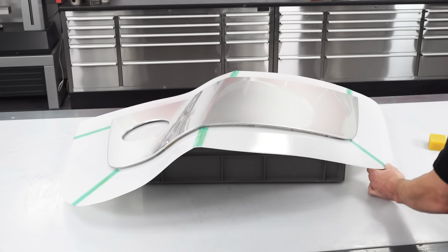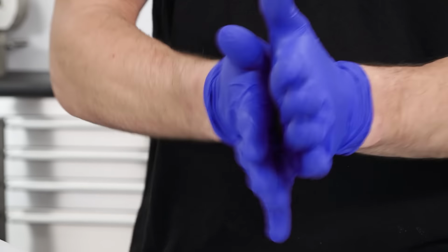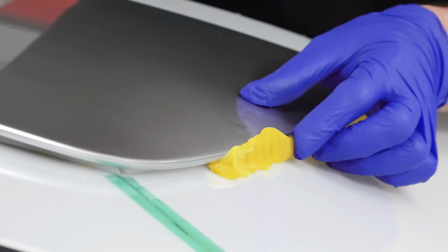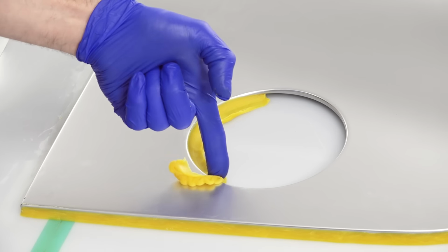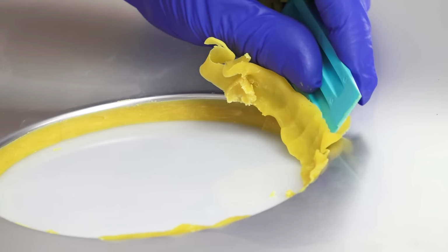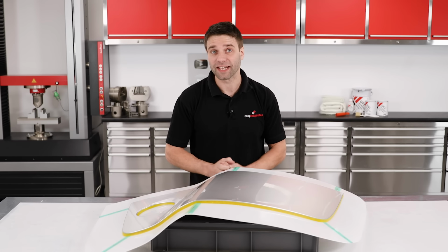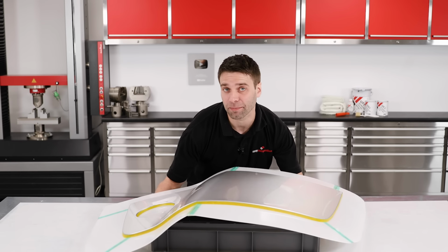The gap between the barrier and the part is then closed and sealed using filleting wax. This wax is really easy to apply, but modelling clay like plasticine will also work for this. The assembly is then put onto a stable support and it's ready to have the mould made. This part's now all prepped up ready, so we can get on now with the first gel coat application.